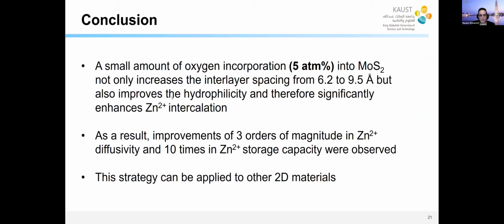So what is the take-home message? Take-home message: just a small amount, 5 atomic percent of oxygen substituting for sulfur in this material can largely expand the interlayer spacing and improve the hydrophilicity and allow the significant zinc intercalation compared to pure molysulfide. We have 3 orders of magnitude improvement in diffusivity and an order of magnitude improvement in capacity. And this strategy, we have data, can be applied to other 2D materials. So that's the first example.